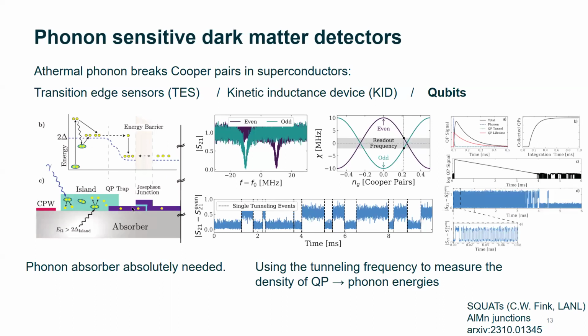After you trap the quasi-particles, depending on the odd or even number of quasi-particles, you see the resonant frequency jump back and forth on this qubit. And in the time domain, you will see a trace like this. So once there's a tunneling of a quasi-particle, you see a jump. This jumping rate really depends on the quasi-particle density on your junction, or say on the island.